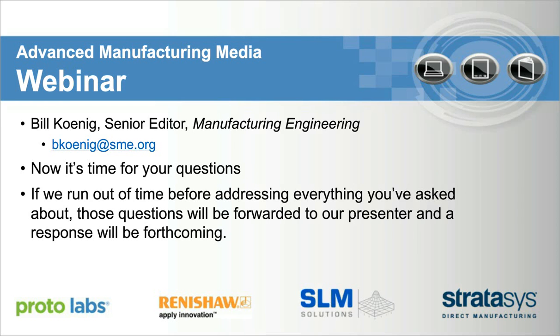for just additive, for different processes, like laser or EBM, because it's not a casting form. There are different solidification mechanisms. Different materials can evaporate, so you have to design for all that. You might have to put more of something, or less of something else, so the chemistry might change. Okay. So it's pretty complex. Yeah, absolutely. Here's another question.